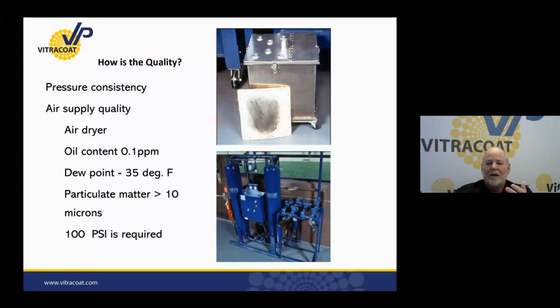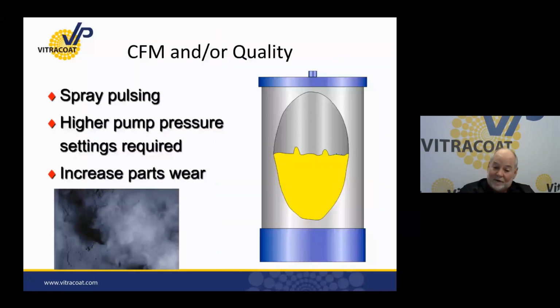I need it for blowdown in my cartridges, if that's my system. I need to have 100 PSI with the appropriate amount of CFM, volume of air, to my fluidizing membranes and to every other component of my powder operation. This particular one shows that I've got the right PSI, but I don't have enough volume of air. And so I get these geysers, and it doesn't fluidize that product because I don't have enough volume of air. And so I'm really going to impact the way that product transfers. So number 7 is, make sure that you're looking at all facets of air, whether it's volume, pressure, quality, or velocity. All those things are critical to a powder operation.